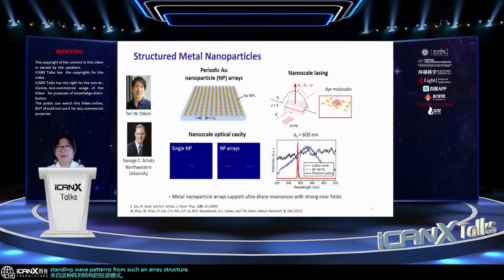In the past, in the Odom group, we were able to integrate this type of nanoscale cavity with dye molecules in solution and achieve lasing at room temperature. You can see that the emission is happening vertical to the sample surface, and the laser emission peak is defined well by the underlying cavity resonance.